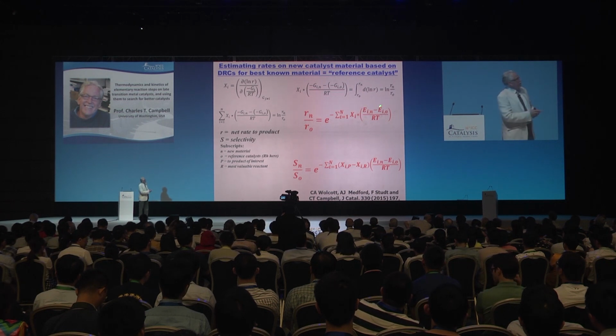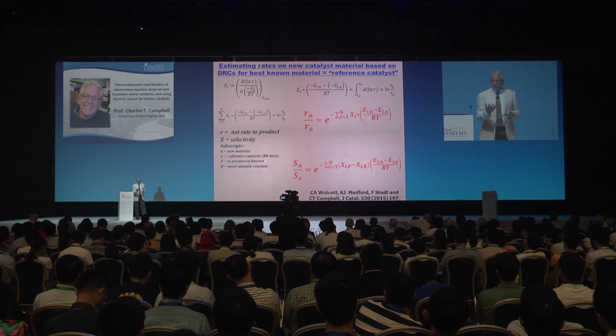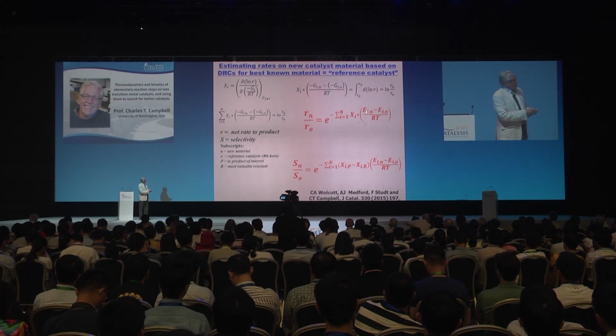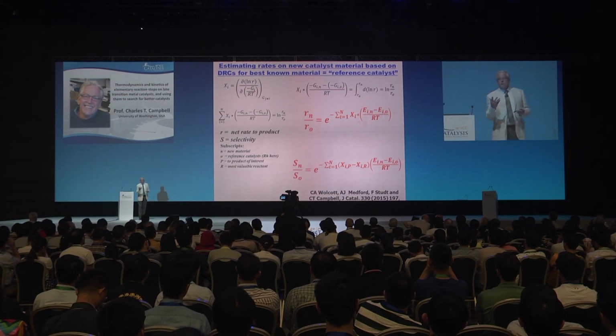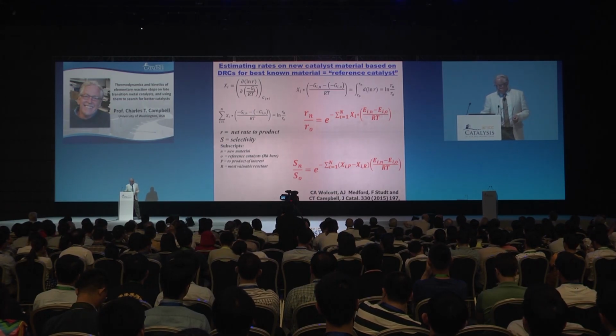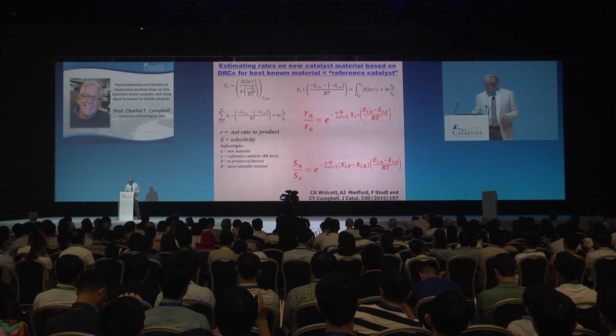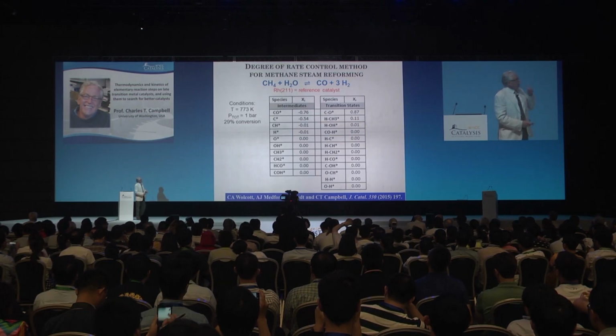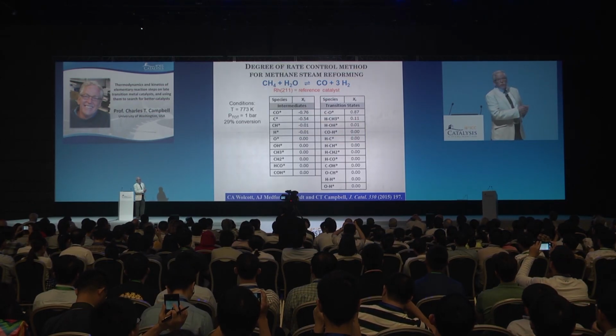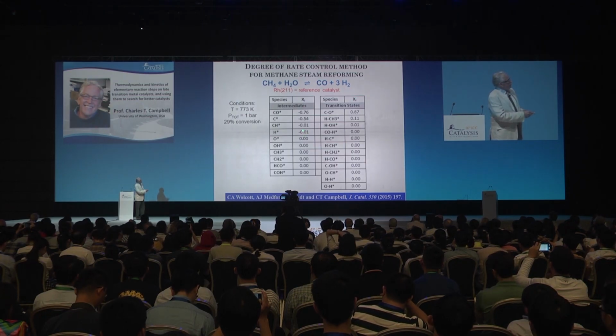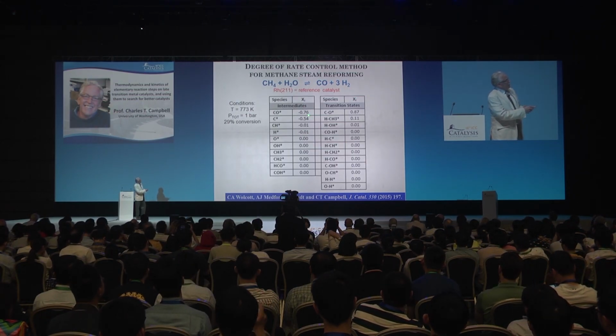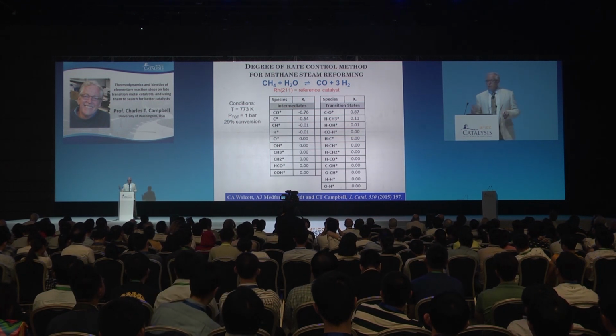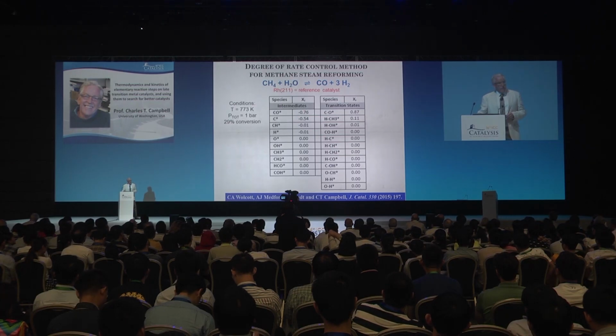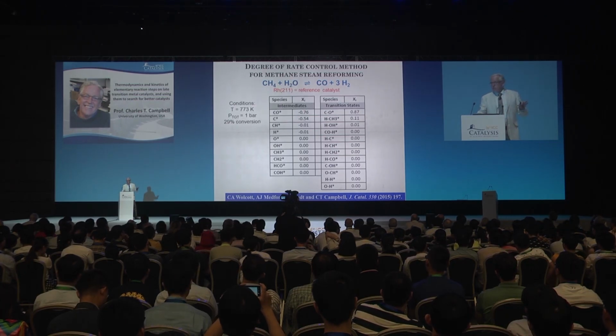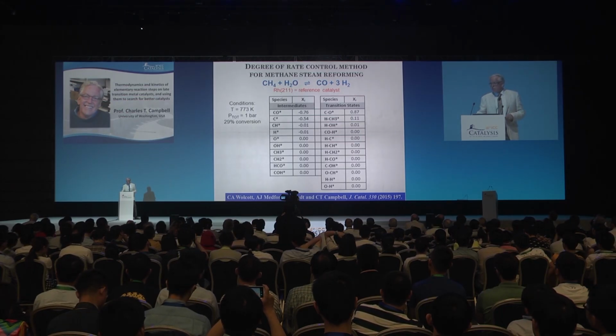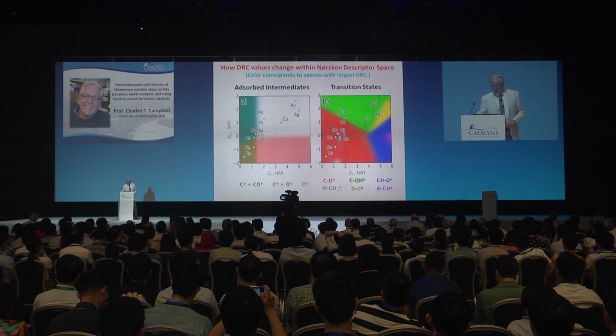That looks like a mess, but remember, this thing is zero for almost everything in the reaction, and so you're only actually summing over a few species here, so you only need a few energies for the new material to predict the reaction rate for that new material. You can also predict selectivities in a similar way. So here, this is that same reaction I was talking about before, methane steam reforming. We took rhodium-211 as a reference material, and for all these species, energies don't matter. You only have to calculate the energies of those on the new materials to predict the reaction rate. And the assumption is that the degree of rate control is the same on the new materials as it is on the reference material for which you calculated the degrees of rate control.